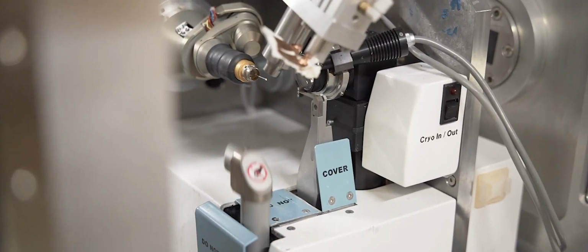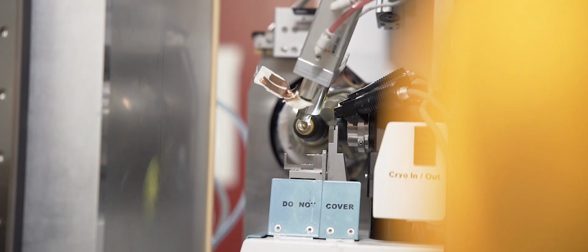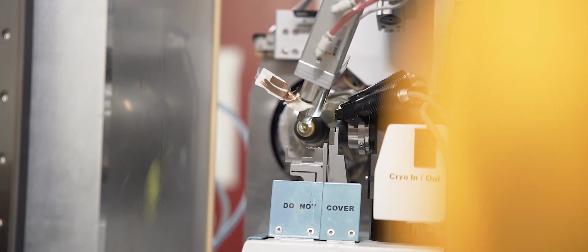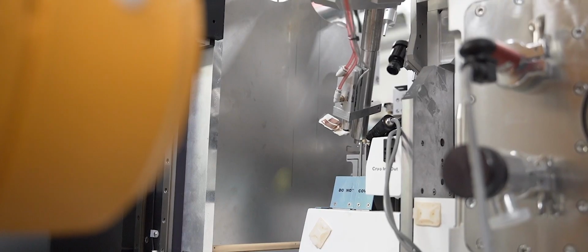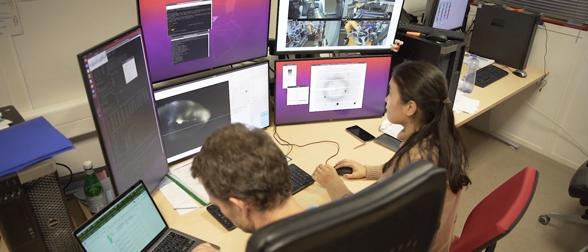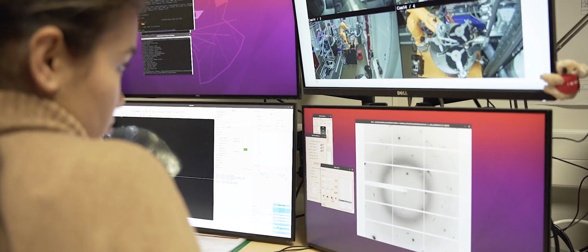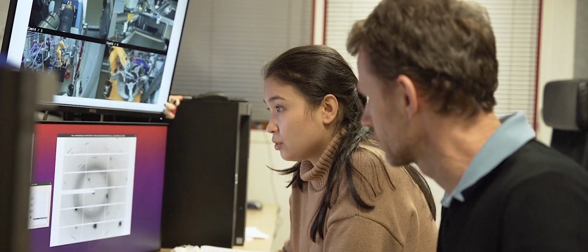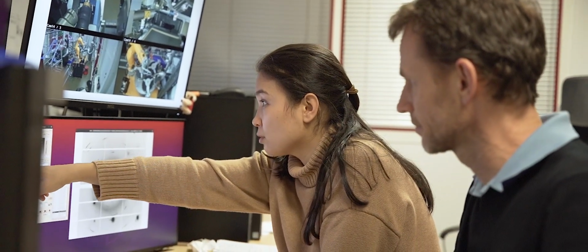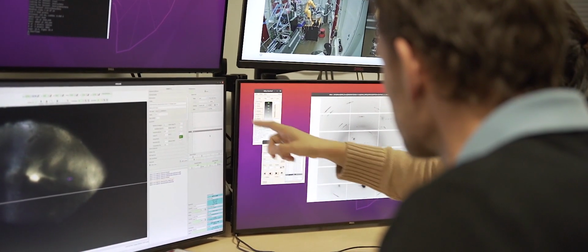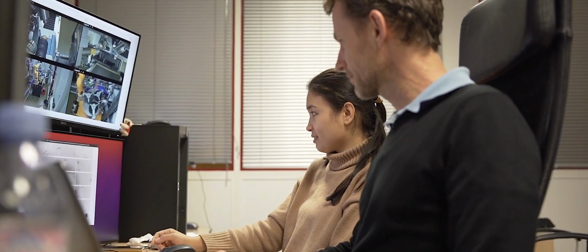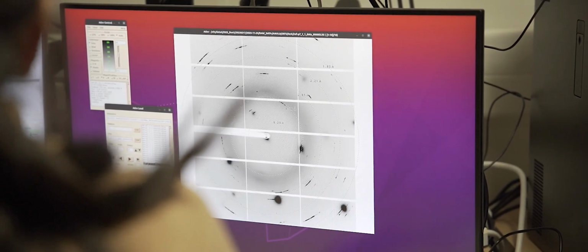The X-ray area detector is an Eiger 9M, which collects X-ray diffraction data at 238 frames per second. A full 360 degrees of X-ray data is typically collected in less than 16 seconds. Each X-ray diffraction image consists of over 10 million pixels, and a graphical user interface called MXCube allows the scientists to set up the crystallographic experiment. This includes loading and unloading samples with the robot, centering the sample, setting the goniometer angles, the detector distance, the X-ray energy, and naming the data files.